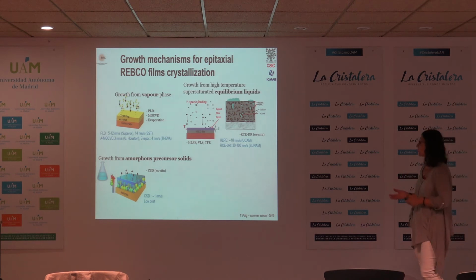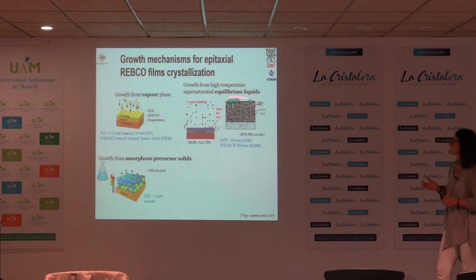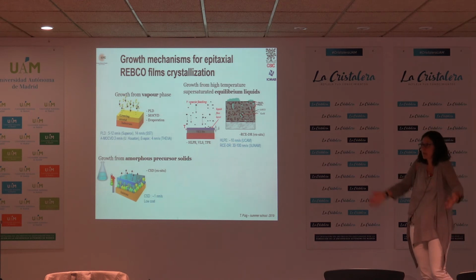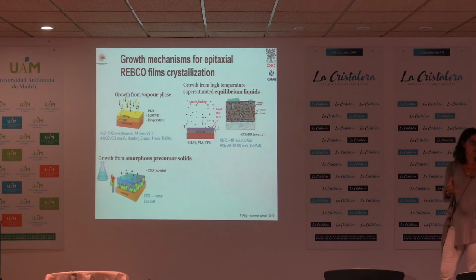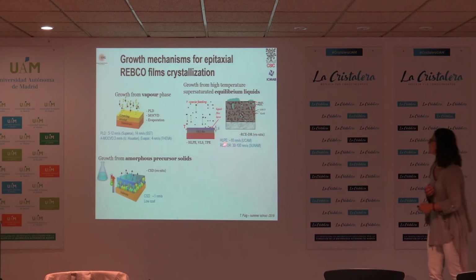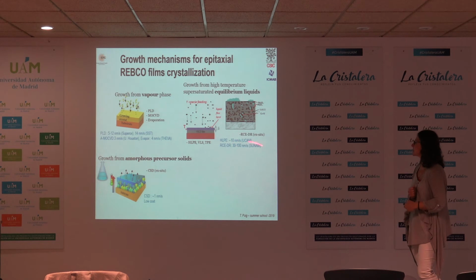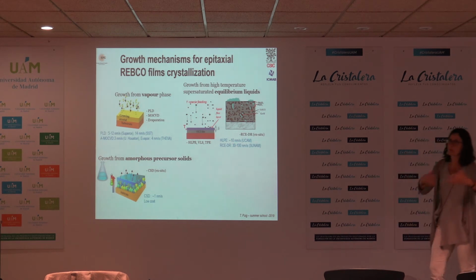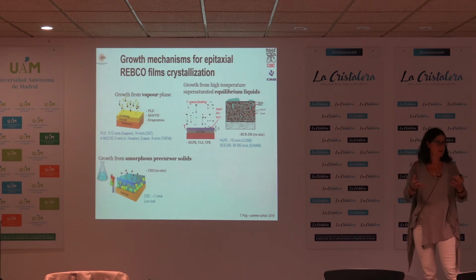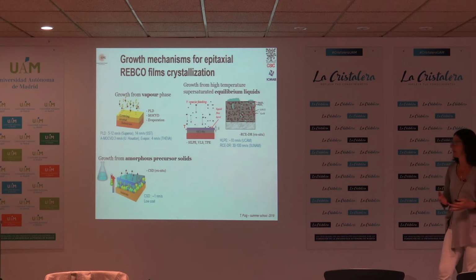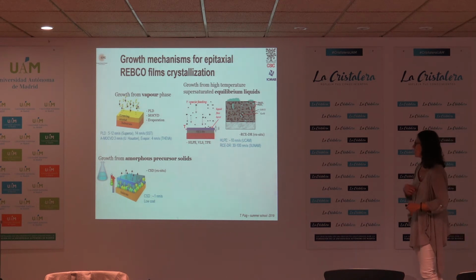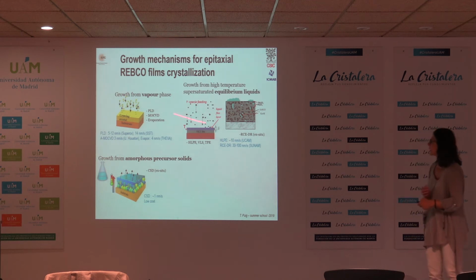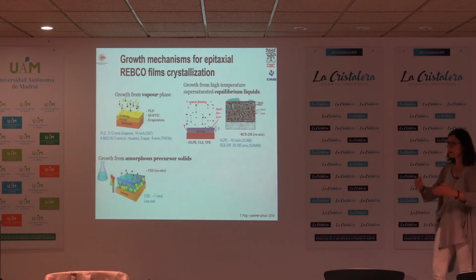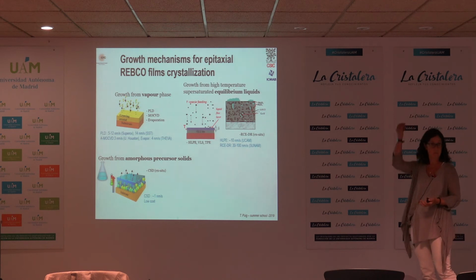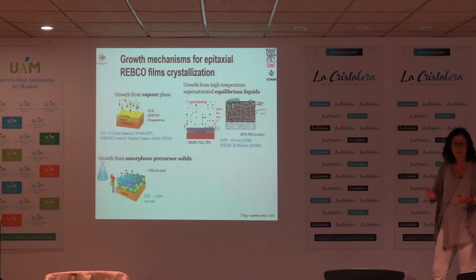If you are able to grow from liquids, from a high-temperature supersaturated liquid, this is the way you grow crystals, if you want to grow a single crystal, okay? If you have a liquid from which you can grow the crystal, that, of course, can then be much higher growth rates, because growth from a liquid to a solid can be very fast because atomic diffusion in the liquid is very high. So systems like hybrid liquid phase epitaxy, where they deposit first a liquid of barium and copper and then they throw yttrium later, okay, they can grow much faster.